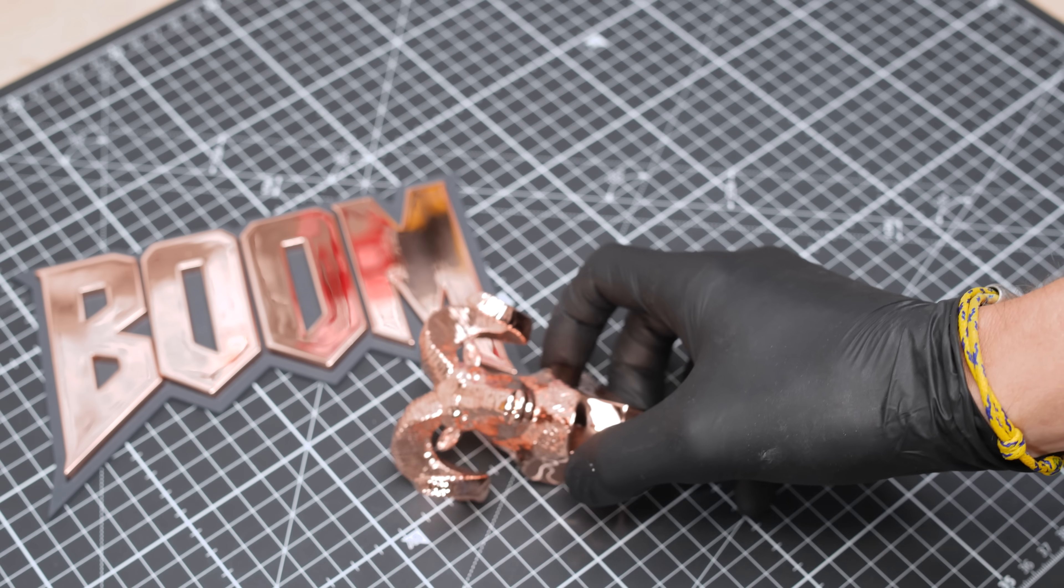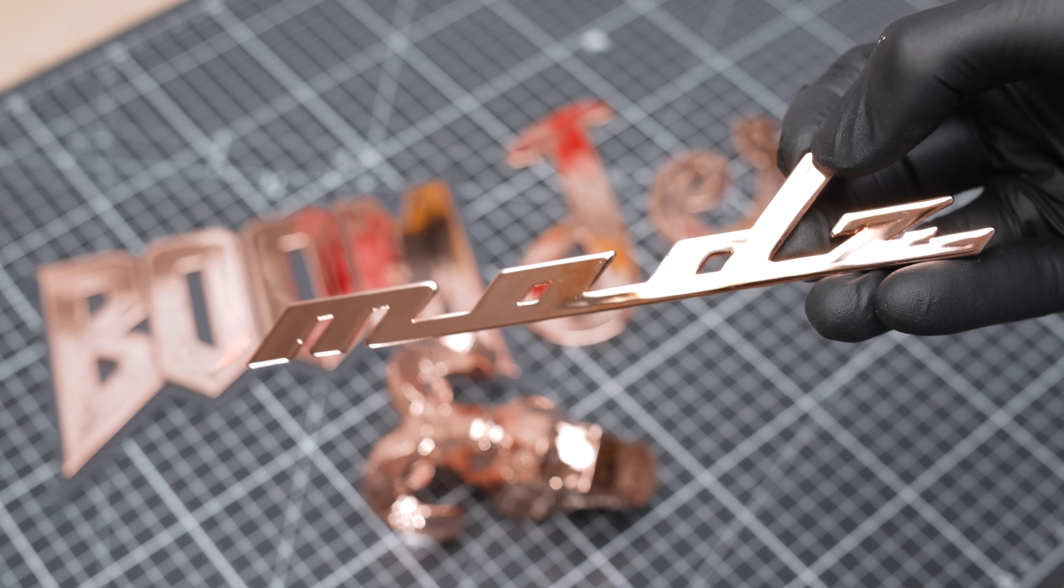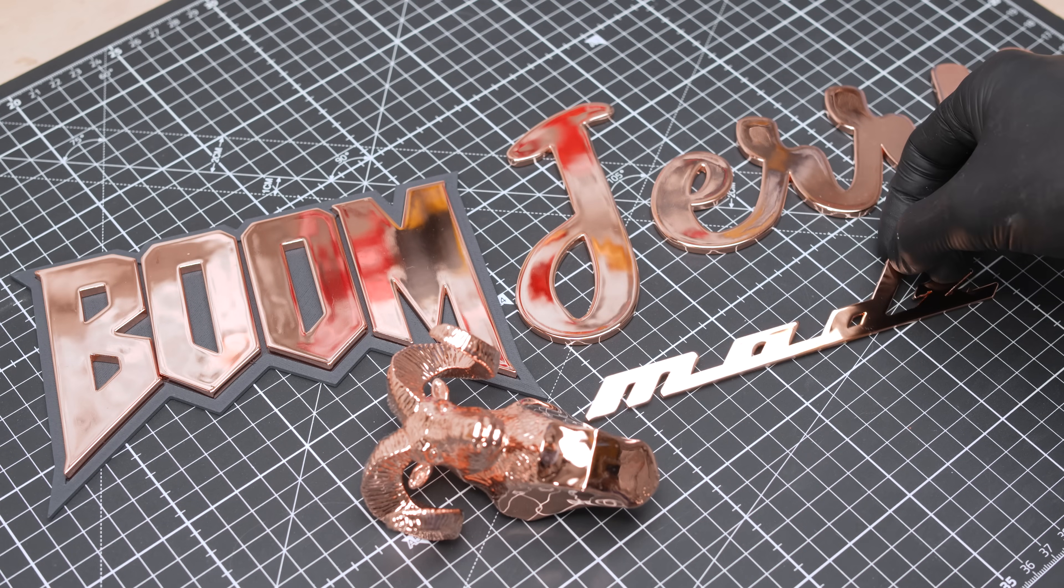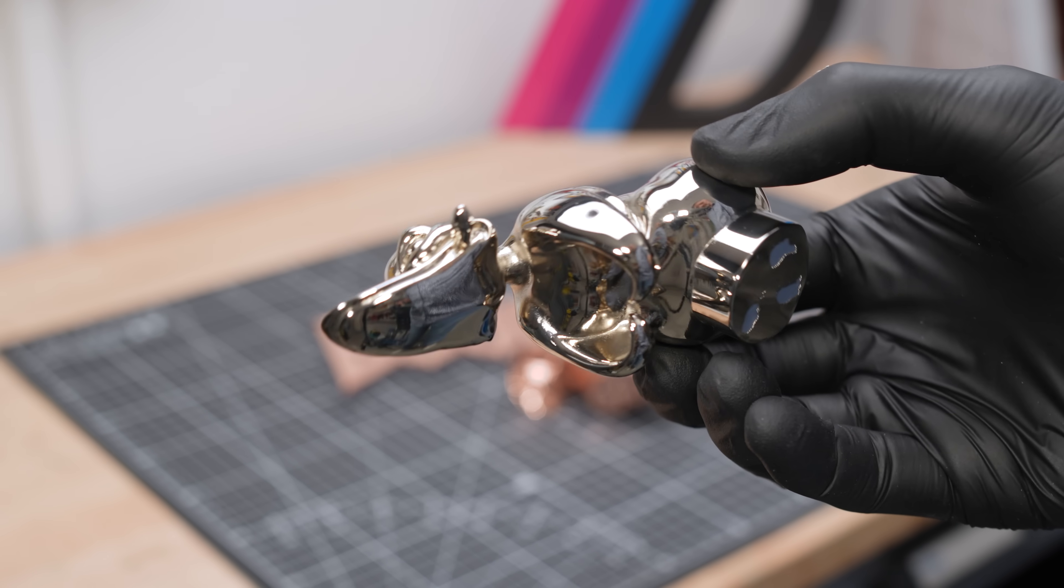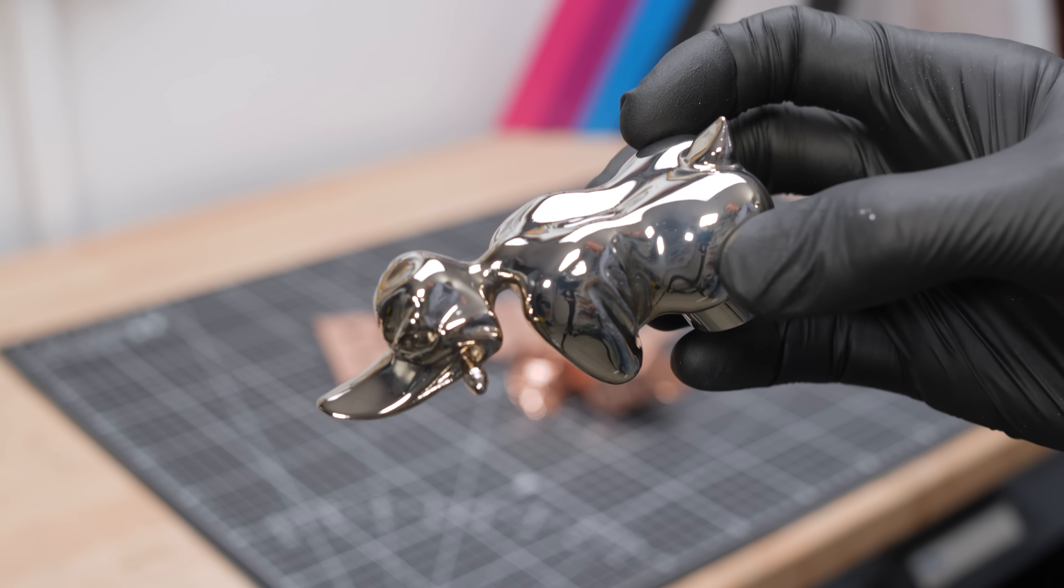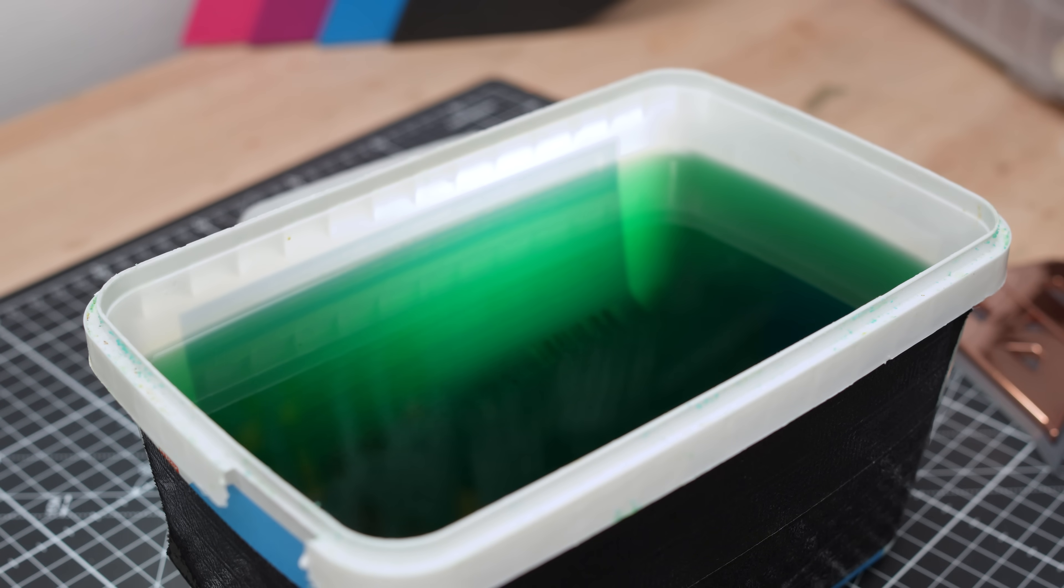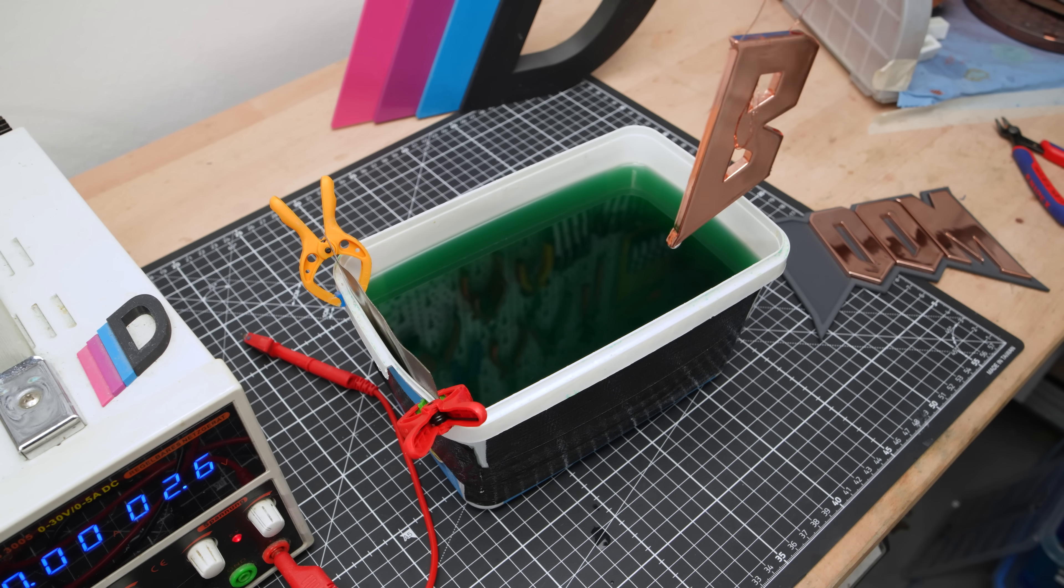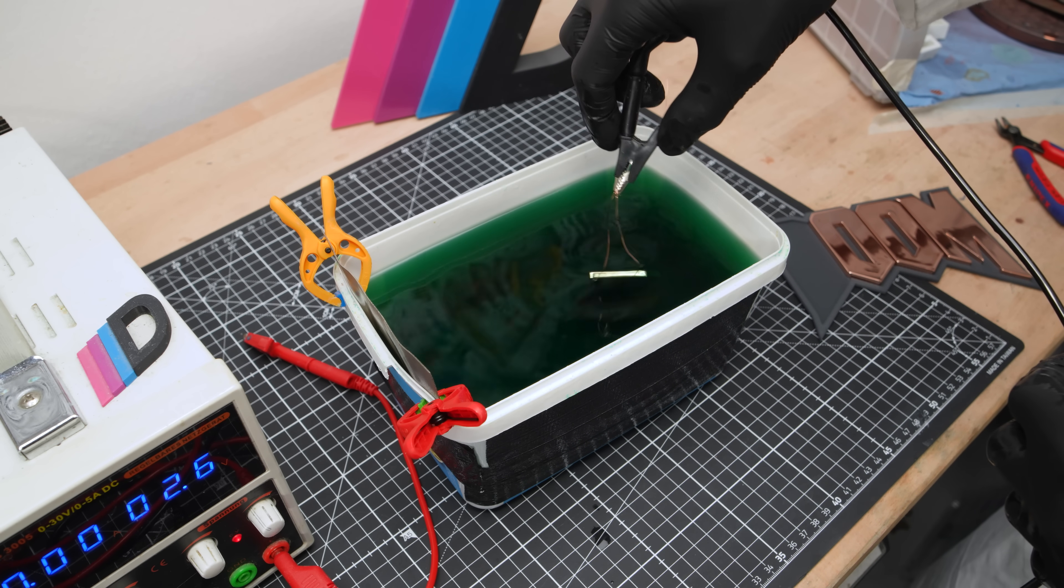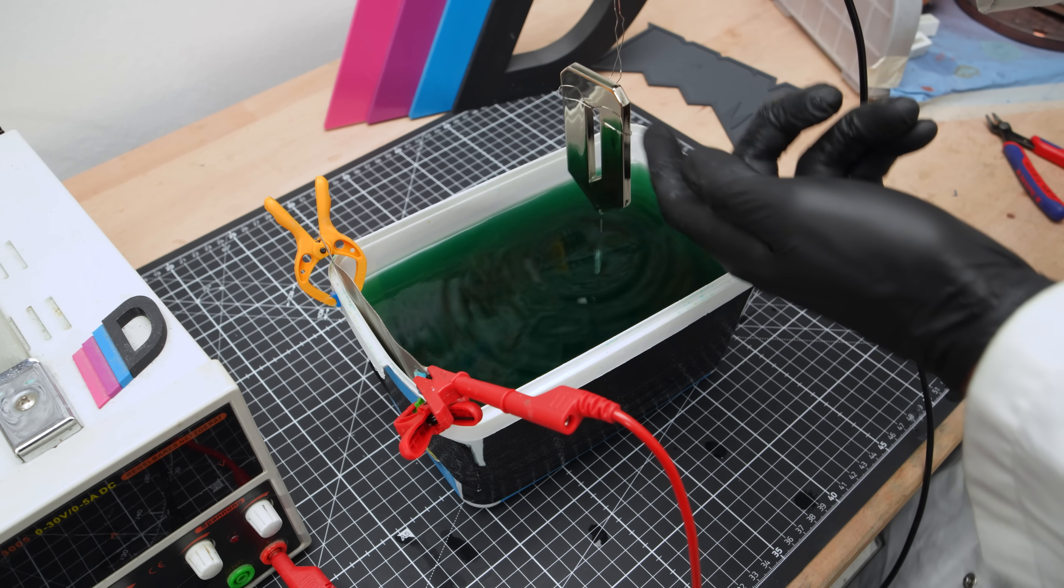So here we go. Everything nicely copper plated, but leaving copper untreated is not a good idea. That's why you can now electroplate other metals on top. Let me show you with this duck. It's bright nickel plated. Not perfect, but hey, good enough. For that I use a nickel electrolyte bath, but pen plating works as well. Another great option is gold. It plates beautifully onto nickel and protects the metal really well. Nickel isn't my favorite electrolyte since it's very toxic and requires excellent ventilation.